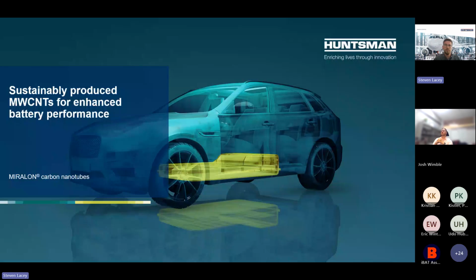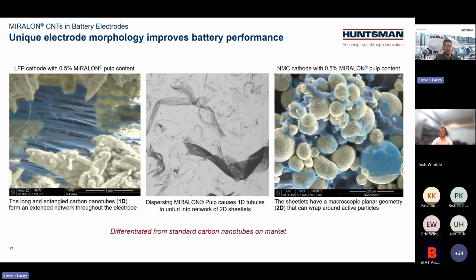So now I'd like to shift gears to our carbon nanotube material that's very unique. The uniqueness comes not only from the production process, which is methane pyrolysis, where we're converting methane gas into this valuable carbon material as well as hydrogen. In this case, the oil and gas industry in particular has a byproduct of methane gas, which they typically flare up into the atmosphere, so you're emitting a lot of CO2. From our process, we can use that methane from the oil and gas industry directly to create two valuable products, this unique multi-walled CNT material, as well as hydrogen. So I'd like to highlight not only the properties and the morphology of this, but also how it can improve battery performance through some third-party validations, as well as a customer success story that I've shared towards the end.